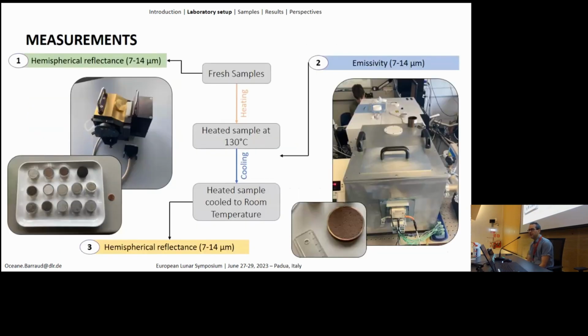And so the scheme of this work, what we did is we have a lot of lunar analogs. We started characterizing them as fresh. So we took hemispherical reflectance on the samples fresh, and then we put the samples in the emissivity chamber, and we in vacuum heated them to lunar temperature, so 130 degrees. We took emissivity measurements on the samples, and then when the samples cooled down, we took them out of the chamber, and we could do hemispherical on the heated sample. So we have emissivity on the heated one, and hemispherical on the fresh and heated, we can have a sort of control on the samples on the spectral features.